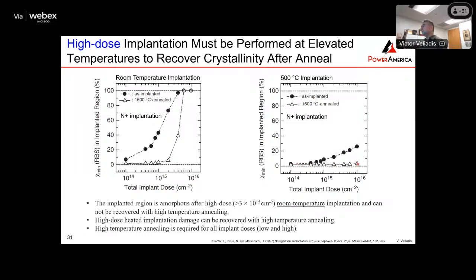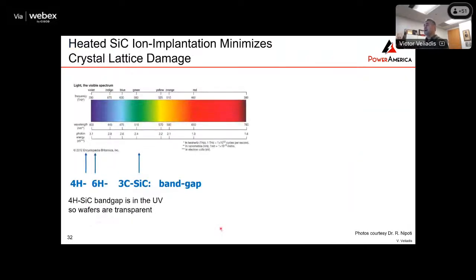And you can see here that you can implant 10 to the 16th centimeter^-2, and this is without the anneal, and this is with the anneal. Once you do the anneal at high temperature, you get a very high quality implanted surface. And the high temperature annealing at 1600 degrees or higher is required for all implant doses.